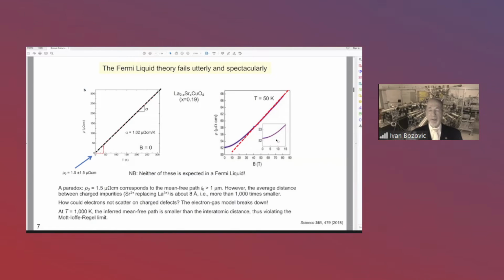Now, if you go the other way to low temperature, then in the sample, upon cooling down, the resistivity extrapolates to zero. And now, from the model, you would conclude that there are no defects or impurities. However, in optimally doped lanthanum strontium cuprate, we have strontium 2+ replacing lanthanum 3+, so it's a charged impurity. And these charge defects are spaced at about 8 angstrom from one another.